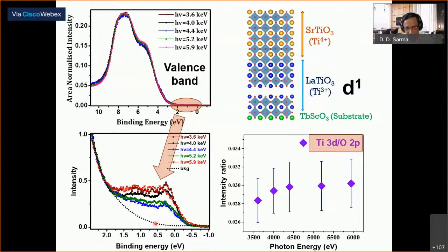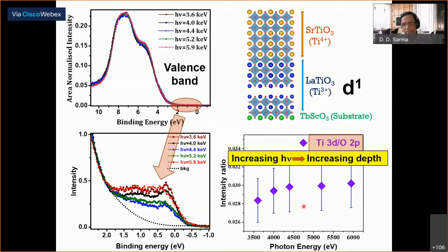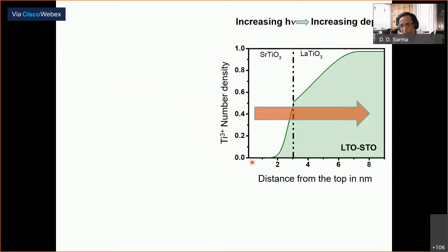First, we look at the intensity of this peak as a function of the oxygen peak, here shown. As I increase the photon energy, that means I'm looking deeper inside, the intensity of titanium 3D is going up, that means this D1 is distributed below, which is as it should be, because lanthanum titanate has one D electron, and this has no D electron. But in order to know if there's anything unusual going on, we have to model and fit this and figure out how exactly the electron distribution is there. And what we find compatible with our experiment is that this is the surface, this is strontium titanate here, this is the interface, and that's LTO. It turns out that LTO dopes electrons into the STO site.